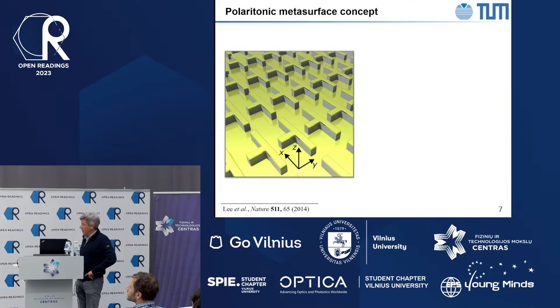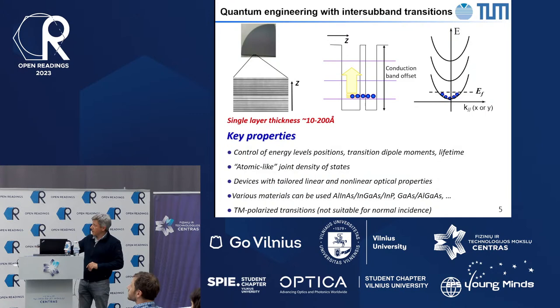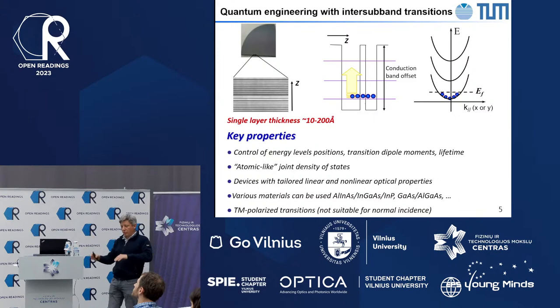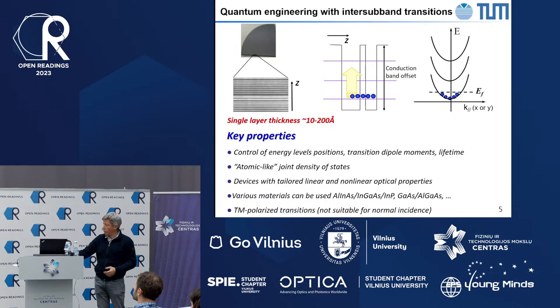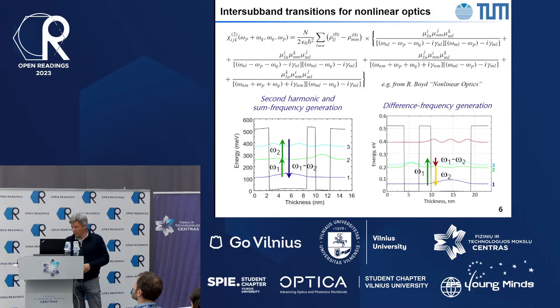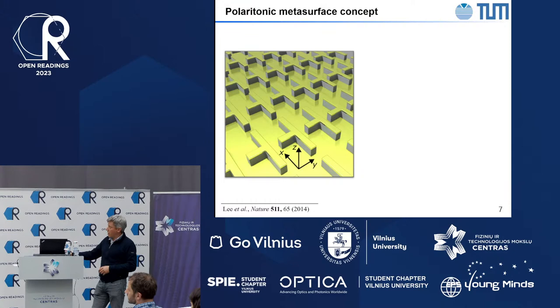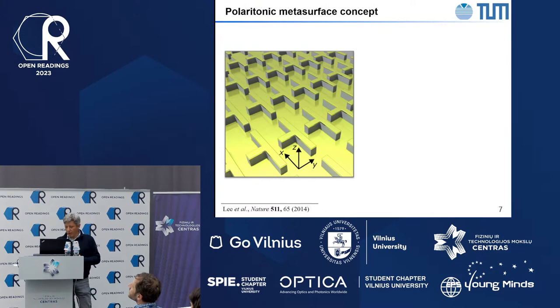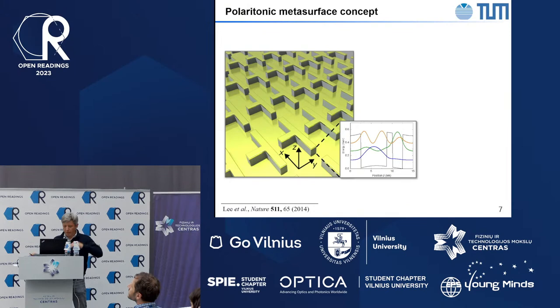So here the idea is the following. You design these quantum wells using semiconductor growth. You design these layers, you get a wafer, you get these layers grown, then you put some metal on top of this wafer, you do wafer bonding, and then you remove the substrate, leaving behind only this semiconductor material. Then you can put a little gold pattern on top of that thin layer of semiconductor material and maybe etch antennas, so that you get this structure where you have gold at the bottom, gold on top, and these are all your quantum wells. These quantum wells are already designed to have this giant nonlinear response for electric field polarized perpendicular to the layers. You can repeat them many times to stack it all up.